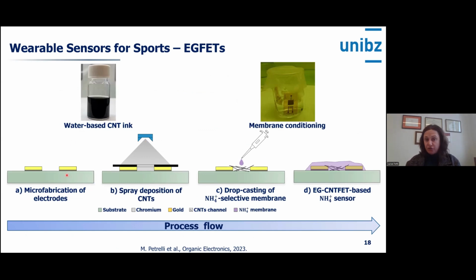As I said, the electrodes are microfabricated. We have a spray deposition of the carbon nanotubes, using a water-based carbon nanotube ink made with commercially available single-wall carbon nanotubes. We drop cast the membrane that is synthesized. There is a membrane conditioning step that is always required for the devices. You see here the devices with the big gate pads. It's not really used, but it's a geometry that we use when we're also functionalizing the gate. So in this case, there is no need. But this is the gate. Those are the two interdigitated electrodes for the source and drain.